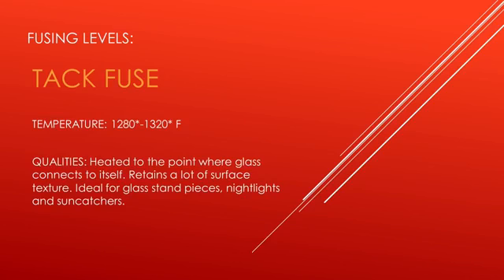What makes it really good is if you're trying to do imagery. So let's say you're trying to do a face, a landscape, or a picture that you're trying to put together, kind of like stained glass. You would tack fuse it. It would retain the glass and not melt as much. Because once you start melting, that's when you start to lose control of what's going to happen and where that glass is going to shift to. The most ideal setting for a tack fuse is for things like stand pieces, something realistic, a nice art piece, night lights, and suncatchers.